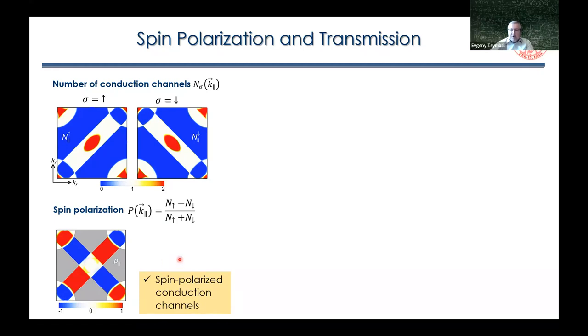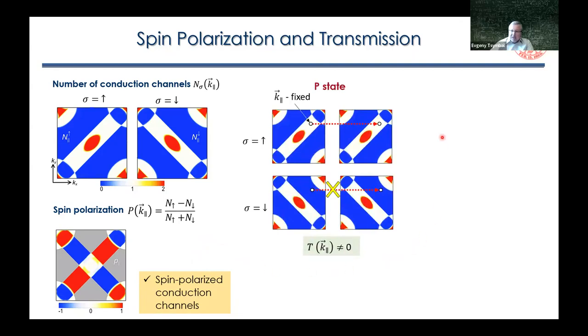So as a result, we should expect spin-dependent tunneling, and we should expect a tunneling magnetoresistance effect, which can be simply explained using this consideration. For example, with a parallel state of the two electrodes, we have the same orientation of the Néel vector in the two electrodes, and we fix a particular k parallel point, for example, here. Then in both the left and right electrodes, we have one conduction channel for spin up. This is white color here. But if you go to the down spin channel, we don't have states here and conduction is forbidden. So this is for the parallel state.